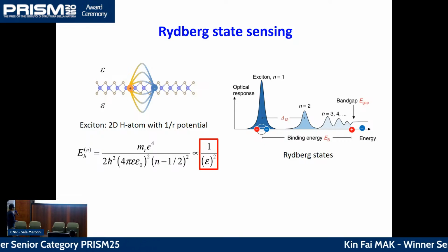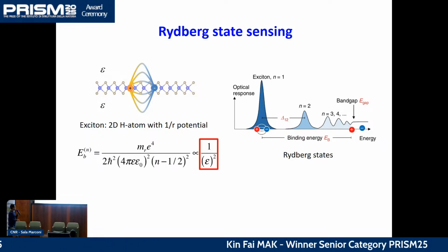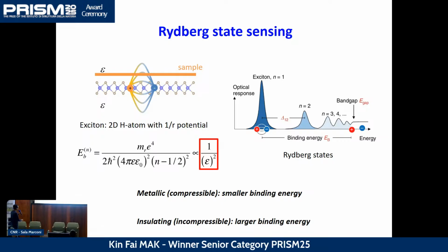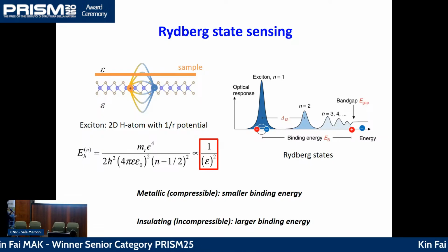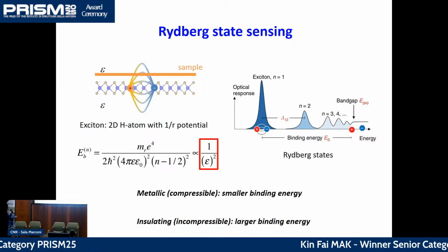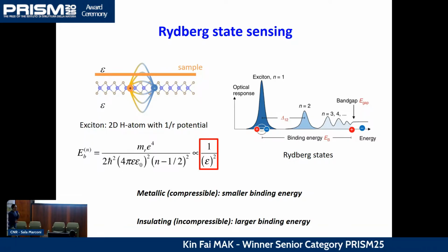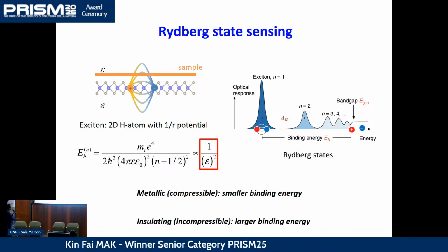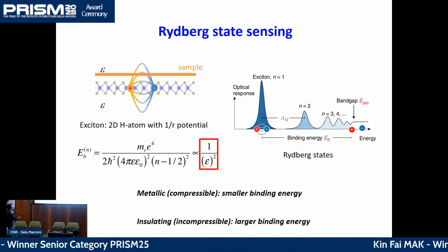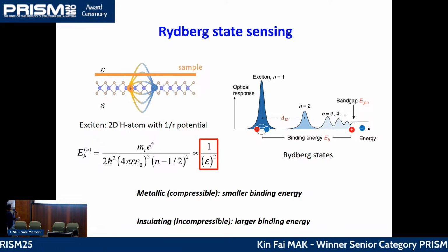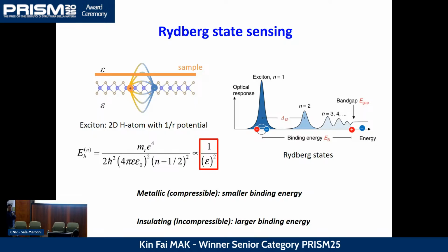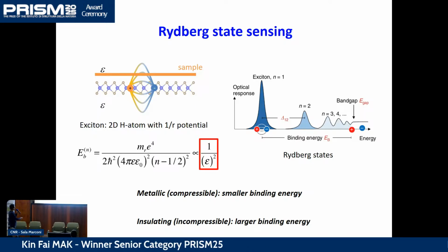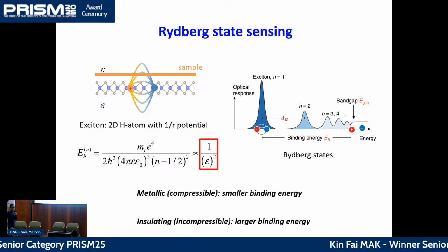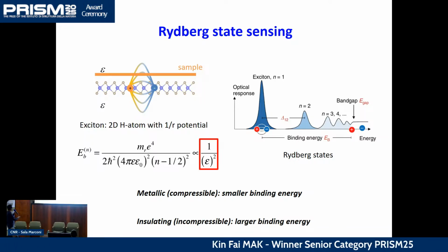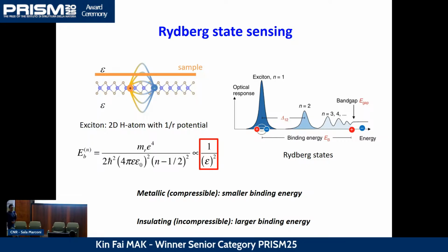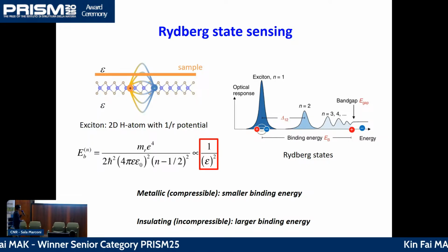Okay, so let's see how we can actually use this property to sense states in strongly correlated electrons. Let's now imagine I have a sample that we can put very close to this semiconductor layer, but not touching it. If the sample is metallic, that would increase the dielectric constant of the environment, and as a result, that will reduce the binding energy of the exciton. If the sample is in some insulating state, that would reduce the dielectric constant, and as a result, that would increase the exciton binding energy. So by just measuring the exciton binding energy of the sensor layer without ever really probing the sample, you would know what's happening inside the sample. Okay, so that's how this technique works.